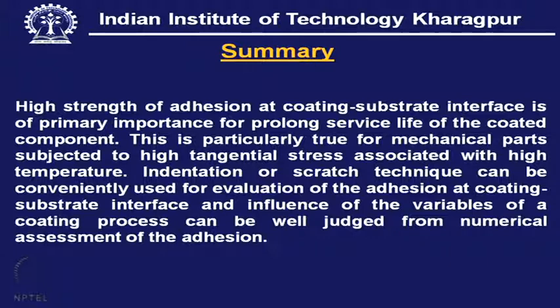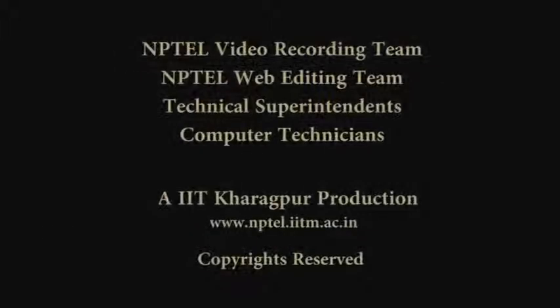To summarize: high strength of adhesion at the coating-substrate interface is of primary importance for prolonged service life of the coated component, particularly for mechanical parts subjected to high tangential stress associated with high temperature. Indentation or scratch technique can be conveniently used for evaluation of adhesion at the coating-substrate interface, and the influence of variables of a coating process can be well judged from numerical assessment of adhesion.